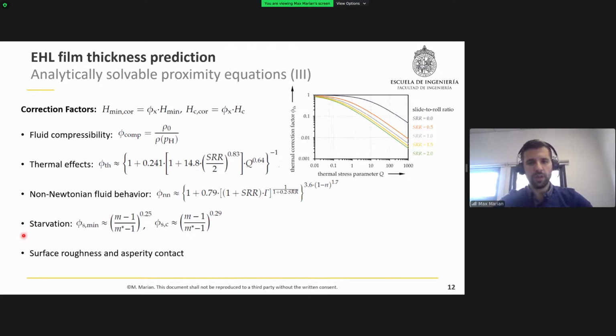Also, in the original derivation of the film thickness equations, fully flooded conditions were assumed. So basically the high elastohydrodynamic pressure buildup can happen at any distance from the contact center. However, there are cases where contacts may suffer from starvation because there are high speeds, highly viscous lubricants, or simply there is not enough lubricant supply. And then basically the starting point of the hydrodynamic pressure generation is closer to the contact center, and the generated transportable lubricant film thickness is basically smaller compared to the one for fully flooded conditions.